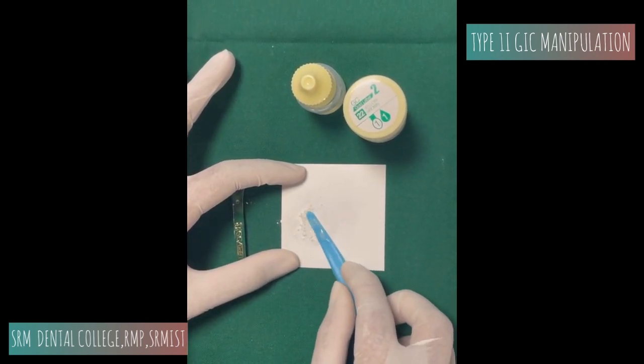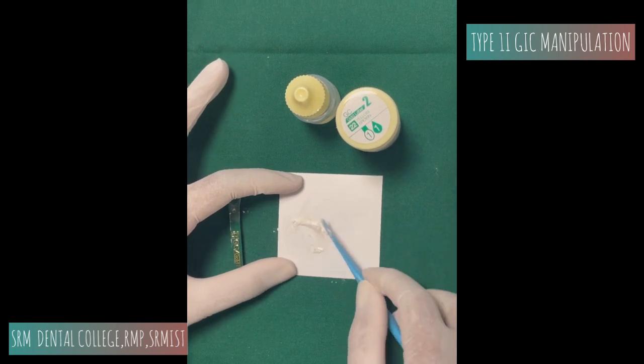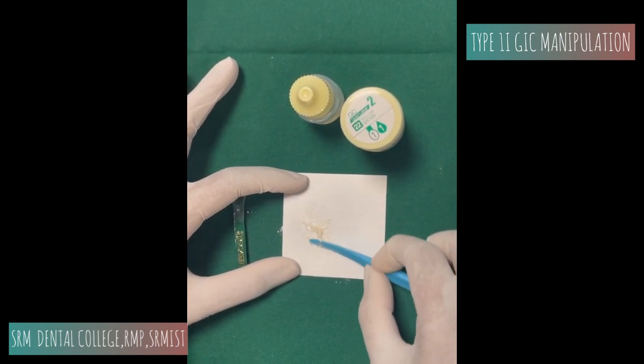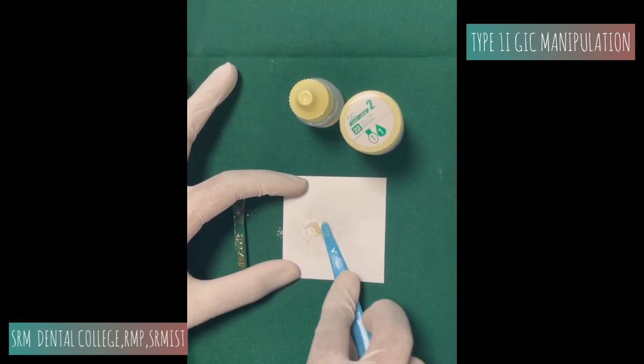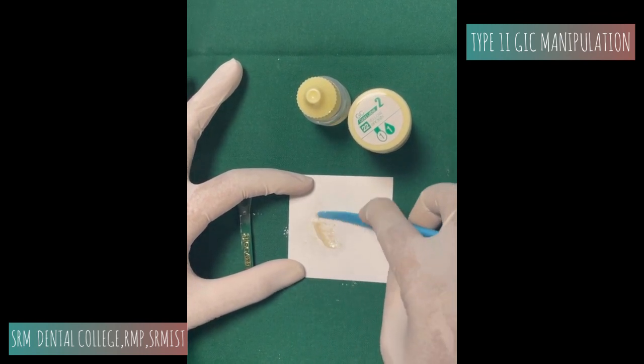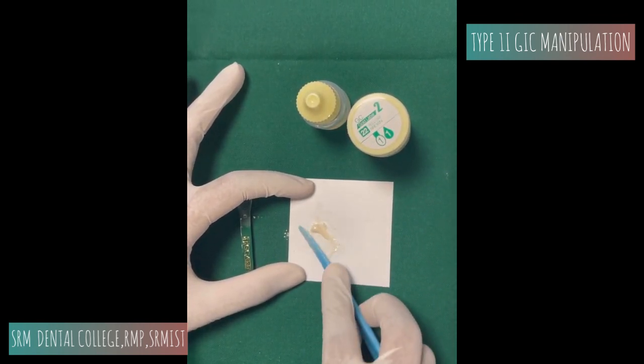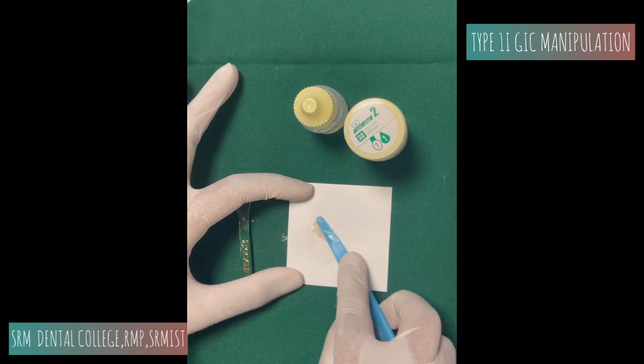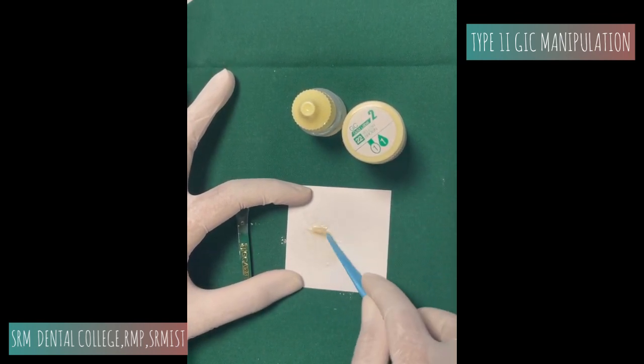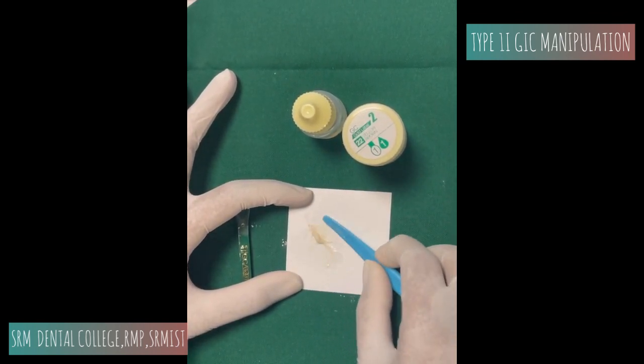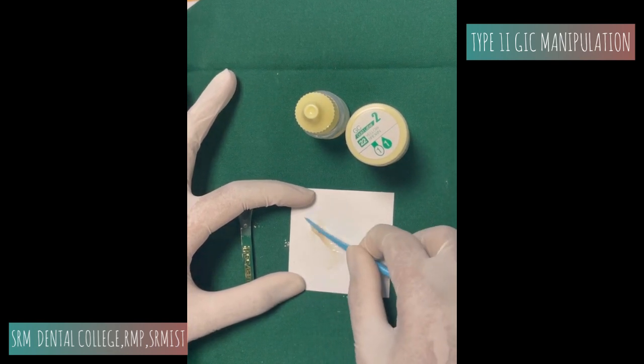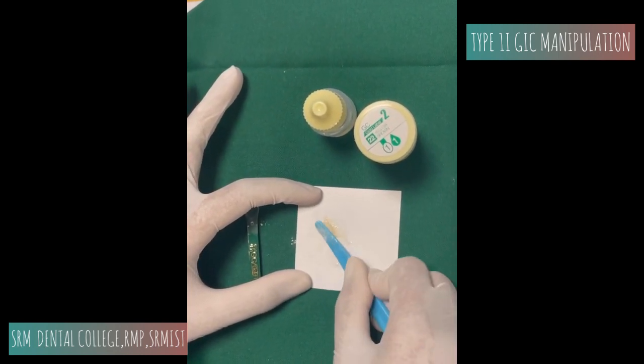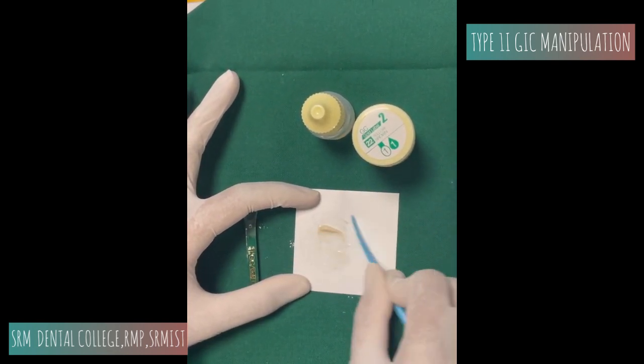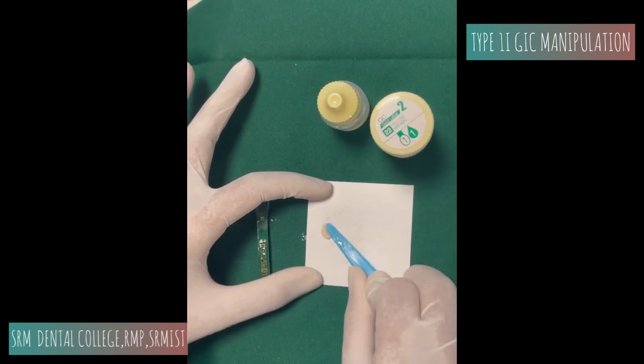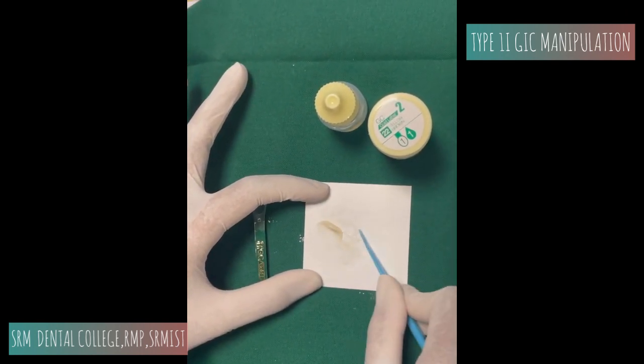Now take the second half, and in the same folding motion, you manipulate till you get a smooth consistency. You do not want to disturb the glass particles. That is the reason you do not do it in a circular motion and you do it in a patting or folding motion. So your mixing time would be around 30 to 40 seconds.